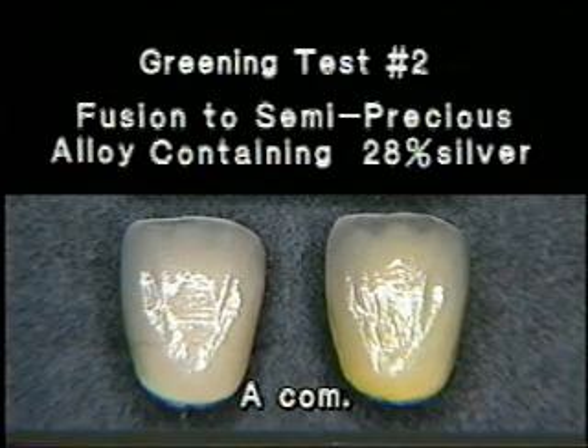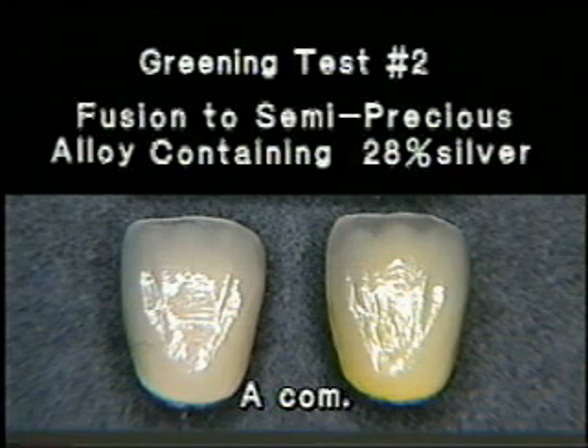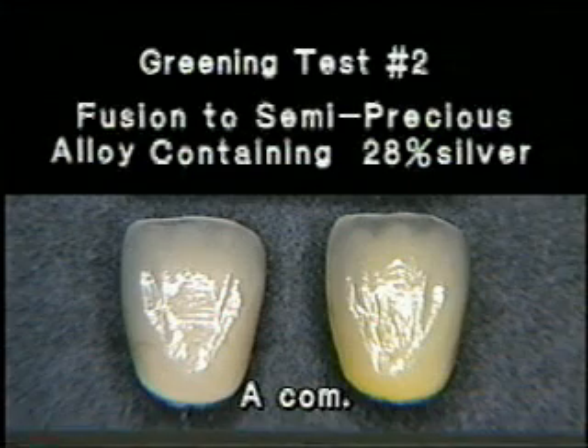Now we do the same test on a real ceramo metal crown. The right piece is an alloy with 28% of silver, and the left nickel chrome alloy without silver. The color shade turns green on the silver alloy.